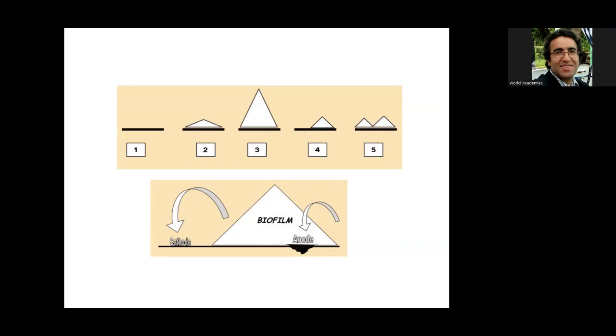We published two years ago one of our papers about hydrophobicity properties of the bacteria that influence its interfacial properties. To understand the hydrophobicity factor, one way is, for example, you dissolve bacteria in one phase, like water phase, and then you mix it with an oil phase, like hexane, for example, or heptane, and then you can see how the partitioning coefficient happens, how the bacteria is distributed between two phases. And we have a case where more than 80% of the bacteria goes to the oil phase. This is why we call it a hydrophobicity factor.